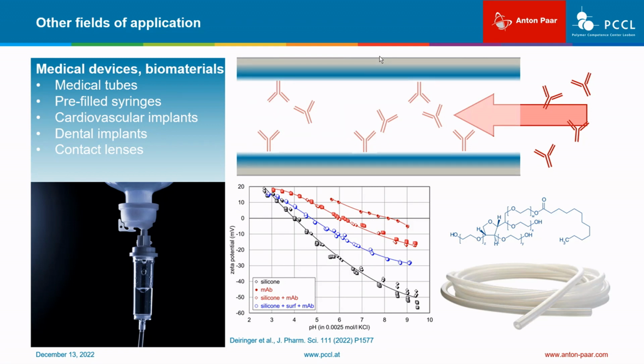Indeed, the capability of this polysorbate to adsorb on the silicone surface and thereby render the surface more hydrophilic was hindering the adsorption of the antibody. The Zeta potential result now confirms a reduction in the surface coverage of the silicone tube by the antibody to approximately 16%. Inge will now continue with the state-of-the-art research at PCCL.